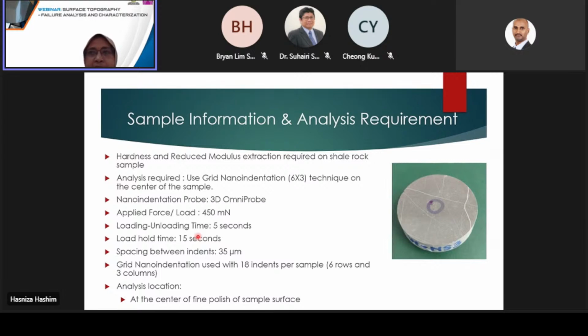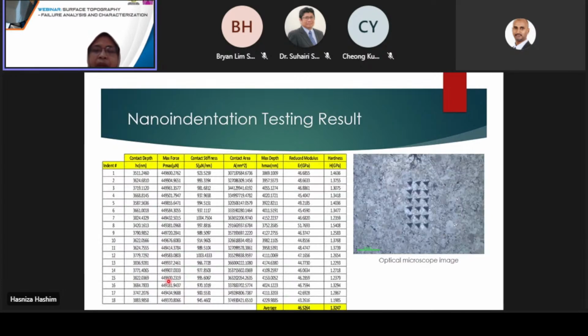Because we are doing the indentations in the same area, and since the surface of the sample is flat, we can generate a lot of information using the grid technique. That means we can do a total of 18 indentations, 6 rows and 3 columns, to get more data. This is an example of the result that can be generated from the testing. If we have a lot of data, we can have a clearer picture of the distribution of hardness or modulus on your sample. This is the image taken using the optical microscope.